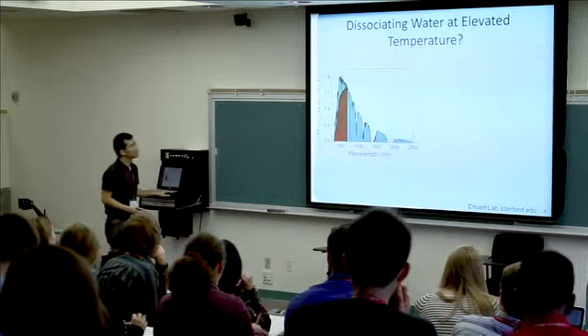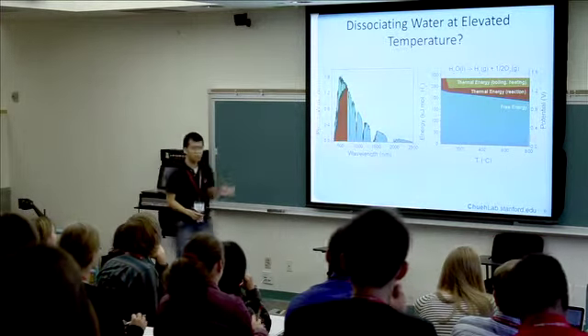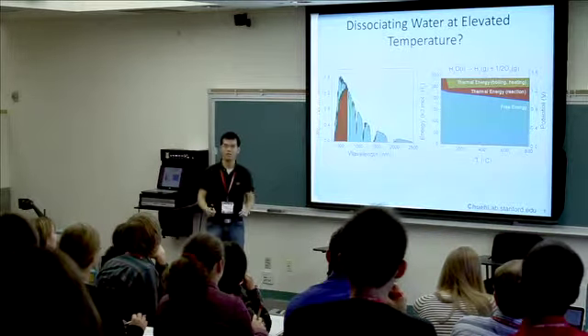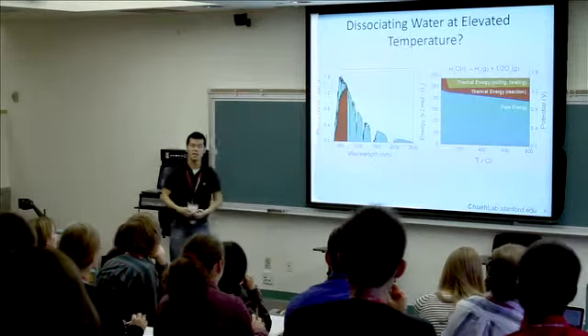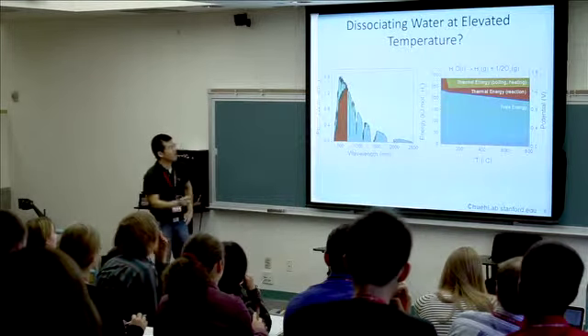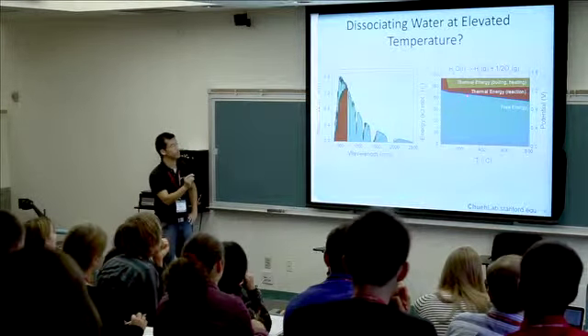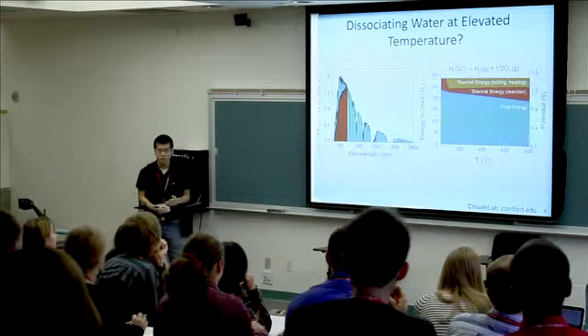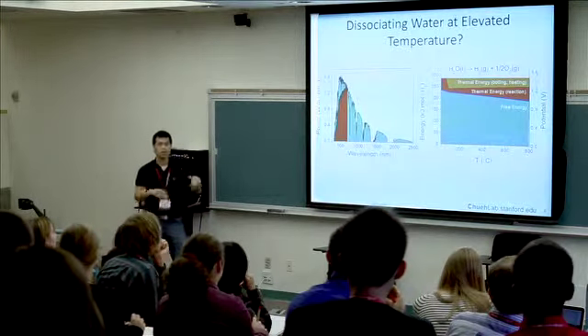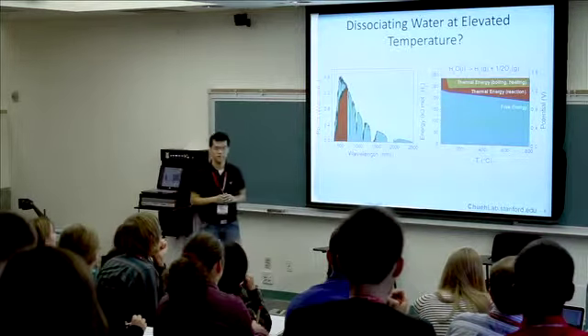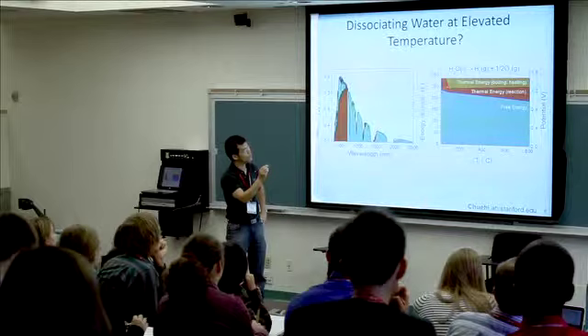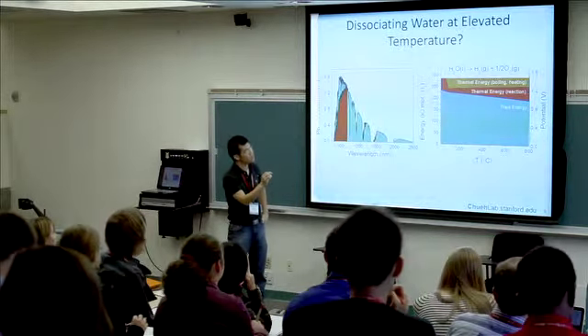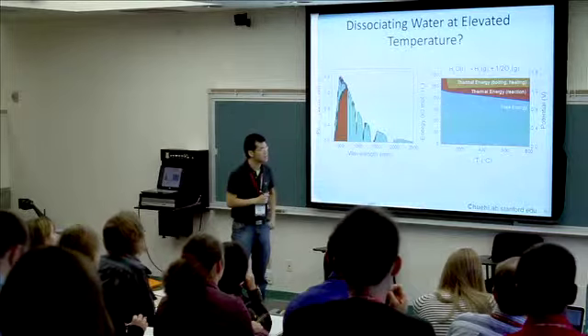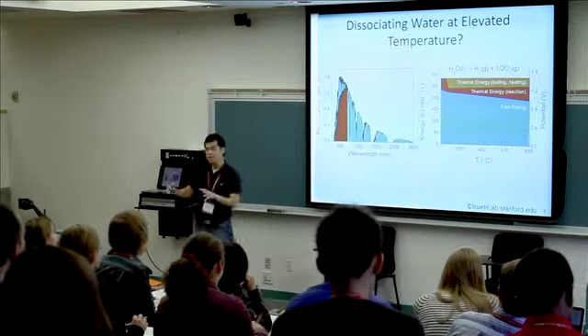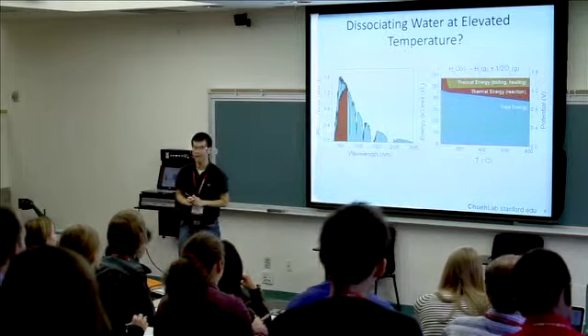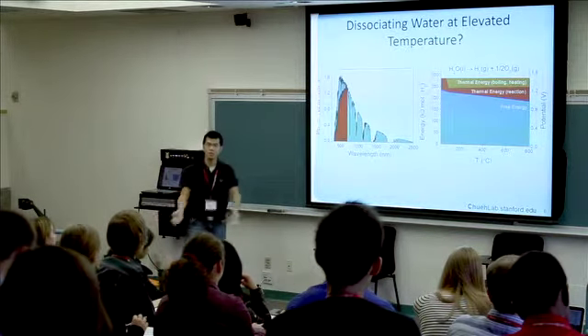So this is one aspect. The other aspect is if you look at the thermodynamics of splitting water. So if you want to take water and turn that into hydrogen and oxygen, there is a thermodynamic cost to be paid. And at room temperature, that cost is about 1.2 volts. But as it turns out, if you increase the temperature of the reaction, you reduce the amount of free energy that is needed to split water. So it actually goes from about 1.2 volt at room temperature, and that goes down to about 1 volt at 600 to 800 degrees Celsius.